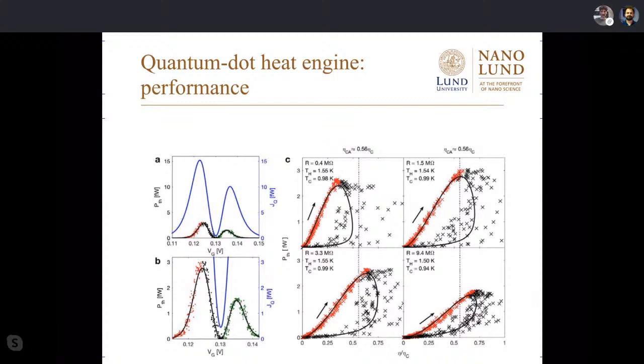From the ratio of the electric power produced and the thermal current that we expect, we can then calculate an efficiency and make these nice loopy graphs here, where in each quadrant you have on one axis the measured power, on the other axis the calculated efficiency for each data point. So for example, the red crowd, which is climbing up to the power peak, each data point gives you a power and an efficiency value, climbing up to maximum power with increasing efficiency. And then as you go closer to the resonance, your power decreases again, efficiency increases, and then it gets very noisy. So this was a disappointment because we had hoped to explore this maximum efficiency regime, but clearly with these data points, we cannot extract anything.